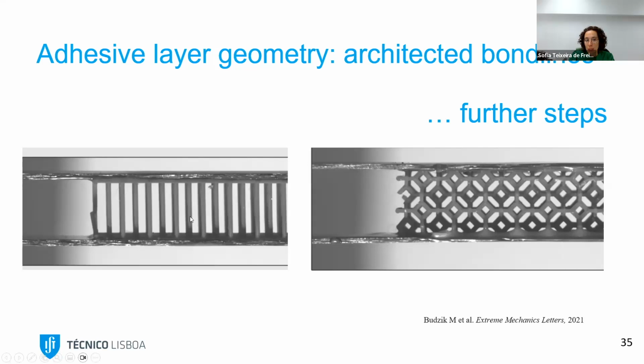Because in this case, with the metamaterials, the geometry is the key factor for the crack propagation. And you can play with different geometries to tune the crack path and create many types of crack deflections, several fracture surfaces, in order to increase the fracture resistance.